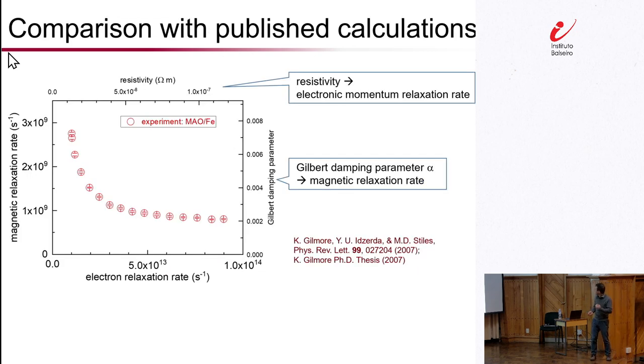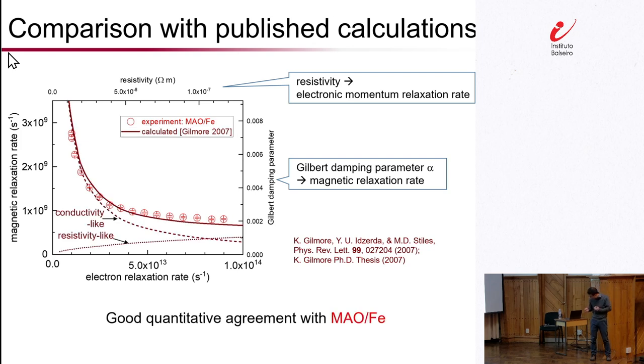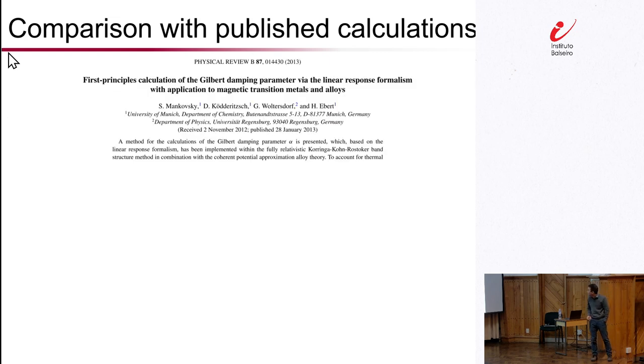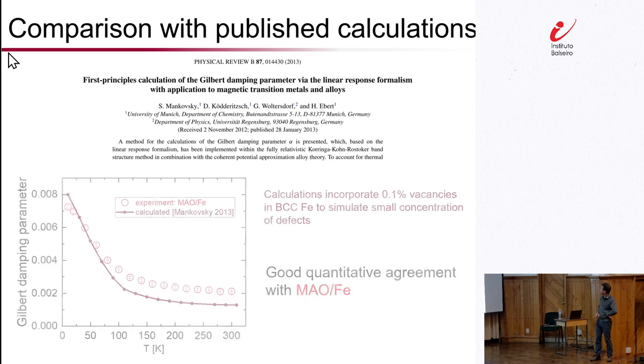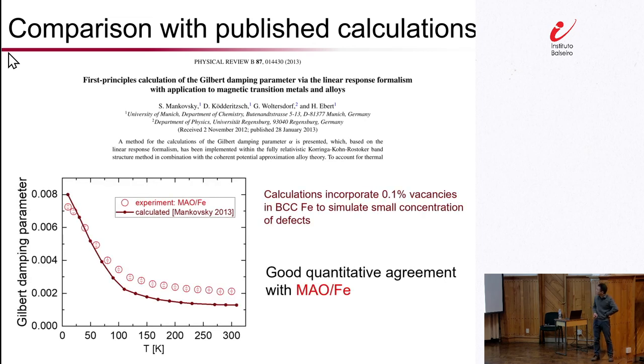Okay, so I think I'm running a little long, so I'll just go through this quickly. This is an example where we compared our experimental results to one of the older theoretical predictions from 2007, where we find surprisingly good quantitative agreement. And here's another theoretical study using somewhat more sophisticated computational machinery. Again, the agreement is quite good, easily within a factor of 2, let's say maybe about a factor of 1.5.